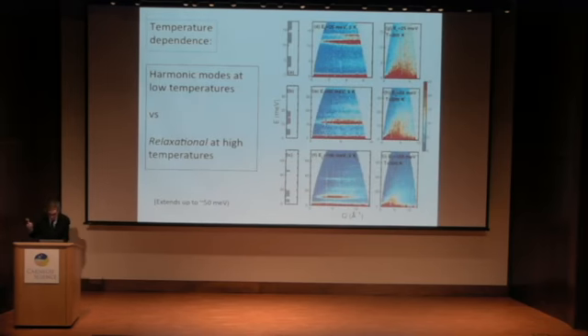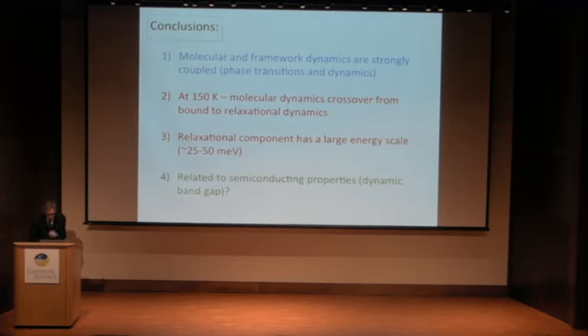So I just have 1 slide left. Sorry. Anyways, the energy scale of this relaxational component actually goes up to incredibly high energies. This is again data taken on MARI. You can see that this broad component extends all the way up to 40 or 50 milli-electron-volts.